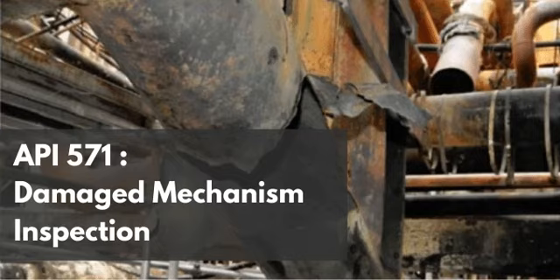The goal of PWHT is to eliminate the locked-in tensile residual stress from the welding process. Residual stress is, at an atomic level, a massive pileup of dislocations within the crystalline lattice. To relieve that stress, you have to increase the thermal energy of the steel enough so that atomic mobility increases. We have to soften the matrix.